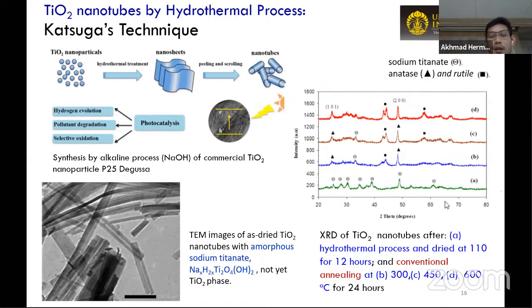A, B, C, D: A is the nanotube after the hydrothermal process. I think this is still amorphous, as the indexing shows that this is still amorphous sodium titanate. When we subject this nanotube to conventional annealing, or calcination, at 300, 450, and 600 degrees Celsius for 24 hours, we can see that the diffraction peaks of anatase and rutile appear here, and the peak of sodium titanate in B, C, and D can be considered gone already.